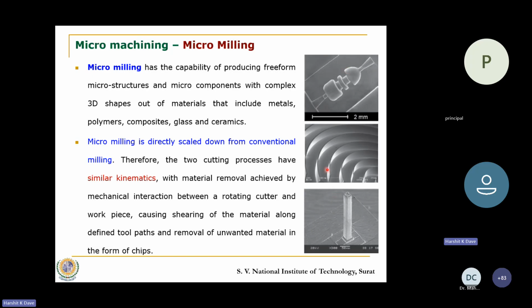If you see over here, the second image, these are the grooves which are generated. Now, if you compare the grooves with these walls, the walls are smaller than the grooves. But the thing is, because this is milling process, this is not additive manufacturing. So we are not producing these walls, we are producing the grooves, and eventually these walls appear. And then there is an example wherein a single pillar, a square pillar is also generated. You can see that the dimension is somewhere around 50 microns on one of the sides. So maybe 50 or 70 by 70 micron size of this pillar. And it appears that if we take this as the base, then probably this is somewhere around 1 or slightly more than 1 mm. So there is a possibility of creating such micro features.